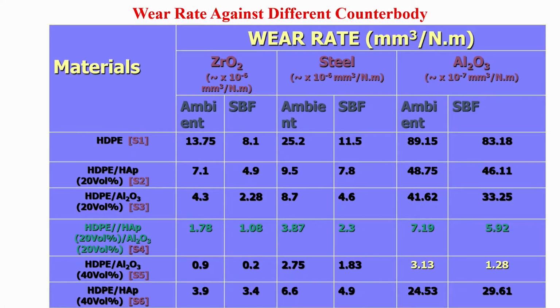Now, wear rate against different counterbody. If you see in this particular case, this is 10 to the power minus 6, this is the order of magnitude of wear rate, and this is 10 to the power minus 7.